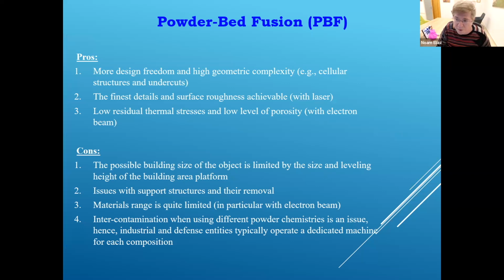Just to give you a sense, people usually don't talk about it, but in companies, usually commercially pure titanium and titanium 6-4 are not printed in the same machine. They will have different machines for each one of the two. And even when you change from titanium 6-4 grade 5 to titanium 6-4 extra low interstitial, it is not recommended because you already presumably have too many contaminants in your chamber.